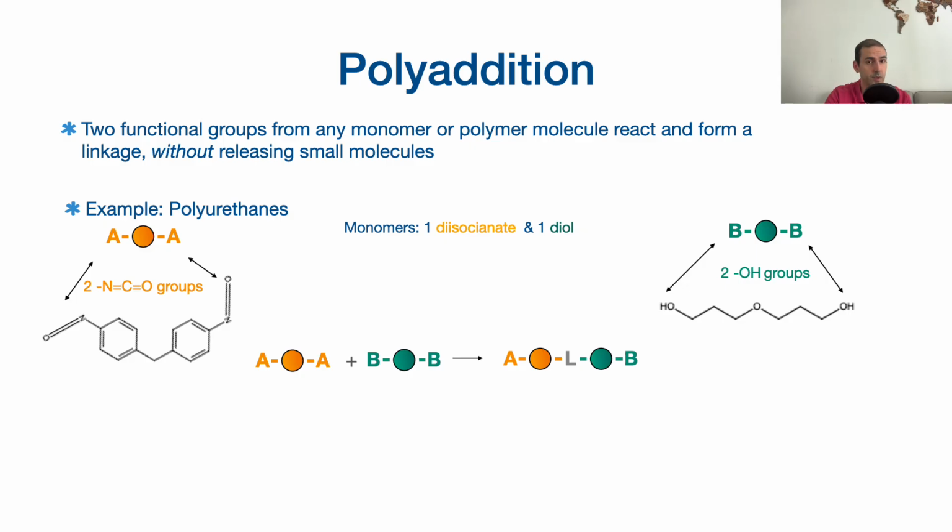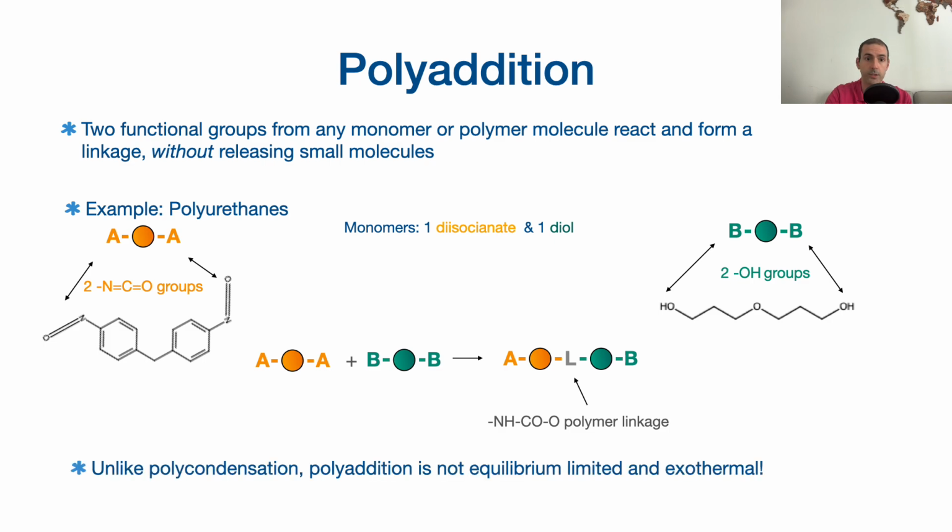As long as the chemistry works and A and B react together, the formalism can be used. So anyway, in this case, with NCO and OH groups, you get an NHCOO polymer linkage. Okay, the first step of a polyurethane. But is this the same as with polyamides? Yet again, a rhetorical question, because of course, no. But it's important to ask this question.